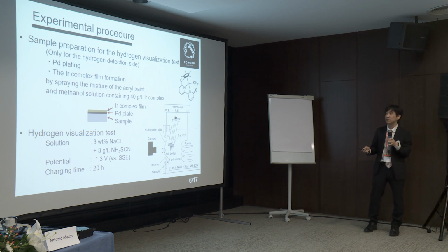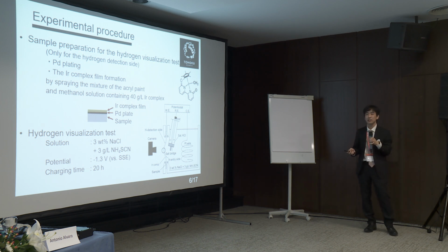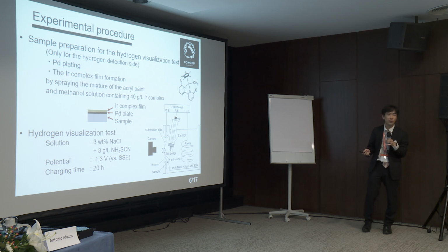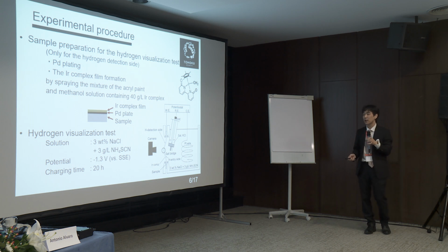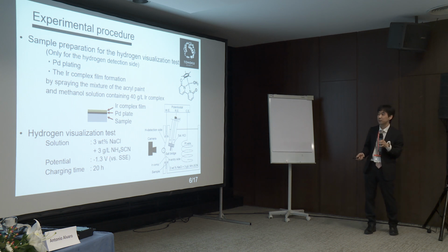One side of the specimen was used as a hydrogen detection site. Only the surface of the hydrogen detection site was plated with palladium and the iridium complex film was formed by spraying a mixture of acrylic paint and methanol solution containing 40 grams per liter iridium complex. This specimen was fixed to these cells, and the cell was filled with 3 weight % sodium chloride aqueous solution containing 3 grams per liter ammonium thiocyanate.